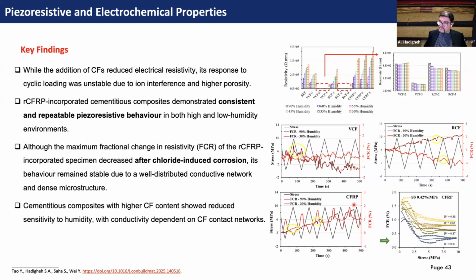performance out of them. So that is probably due to the agglomeration of fiber inside concrete or alignment of fiber inside concrete. But with CFRP powder inside concrete, I think the dispersion is better. You have denser samples, so you have better networking of electrons and conductive materials inside your cementitious material.